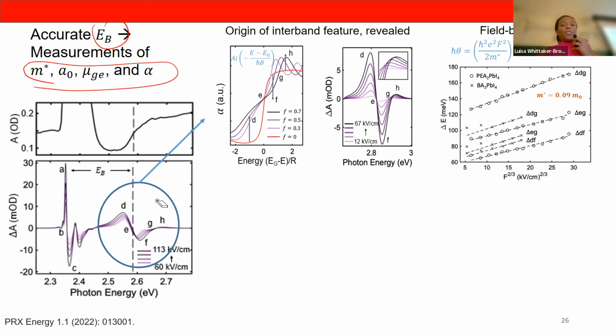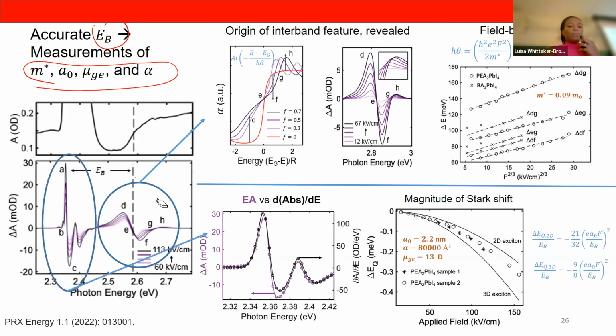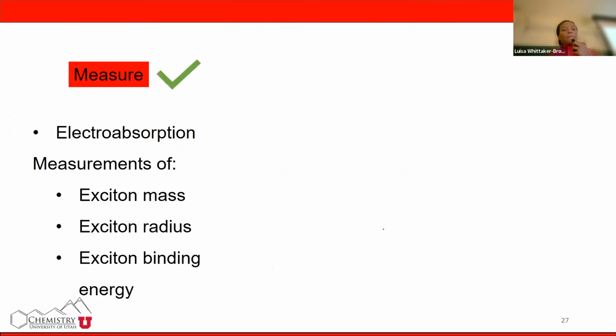band edge feature. On the other end, if we don't fit it to the two-third, but we have the applied field, then we can get all the rest of the information here, right? And then we will notice that even though we are modeling a 2D exciton, these materials really don't fit 2D, and we are using gallium arsenide models, right? So it doesn't really follow the 2D excitonic features that you will see in gallium arsenide or 3D exciton. So it's something in between that we have to eventually figure out. Okay, so we know how to measure.